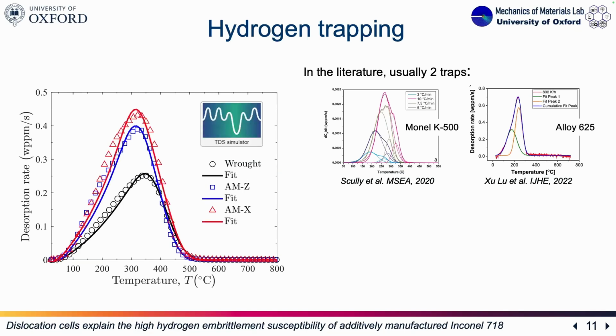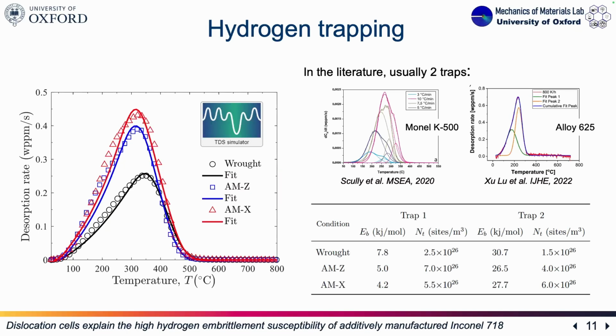So I performed this fitting, which was pretty good for my purpose of just comparing one condition to the other. And I obtained the binding energy and the trap density for 2 different traps for the 3 conditions. The first thing we can observe is that in general, the binding energy was higher for the wrought in both of the traps, while the density of traps was higher in the additive condition.